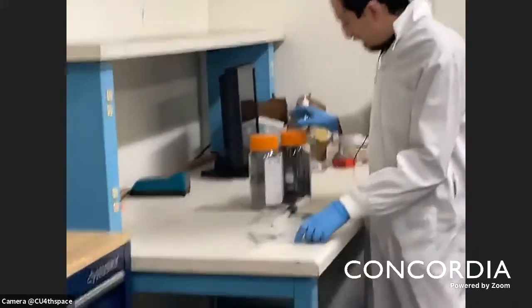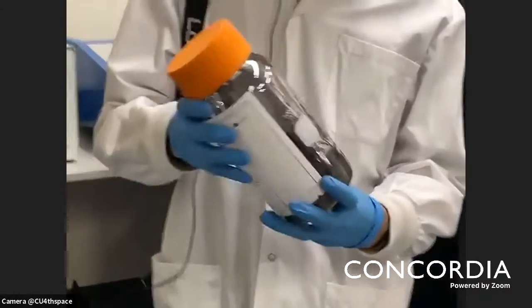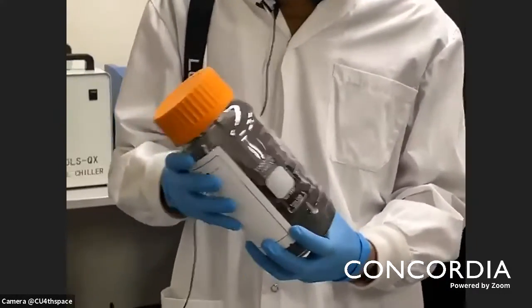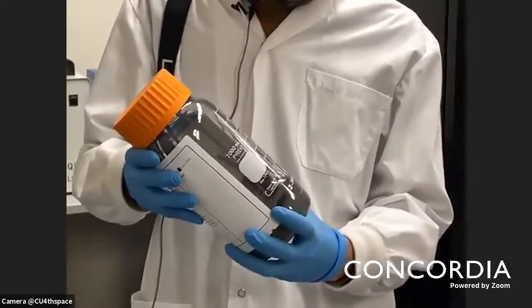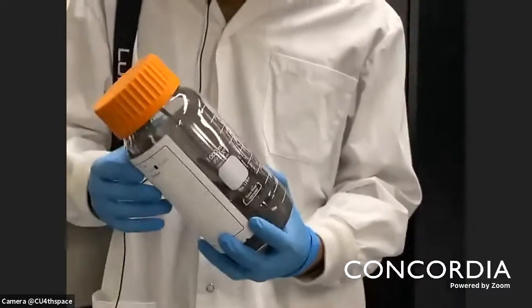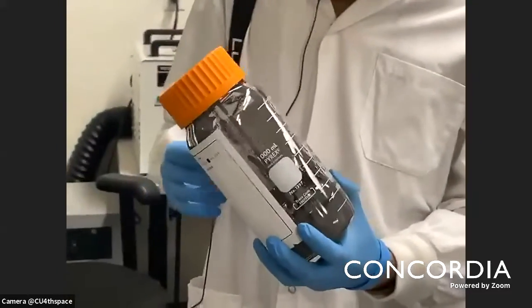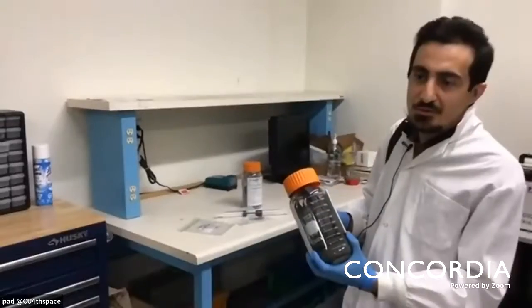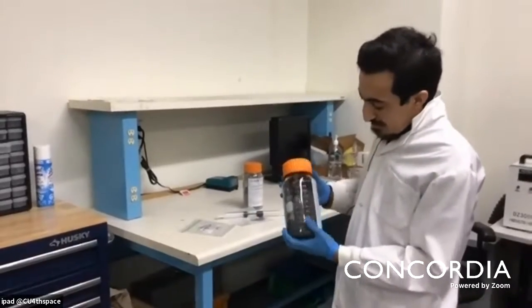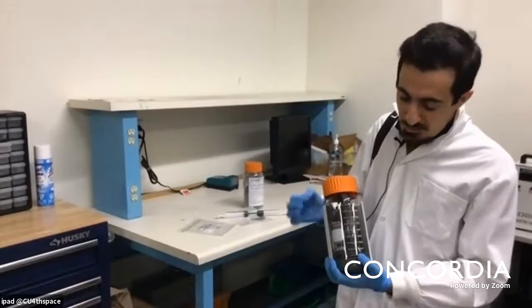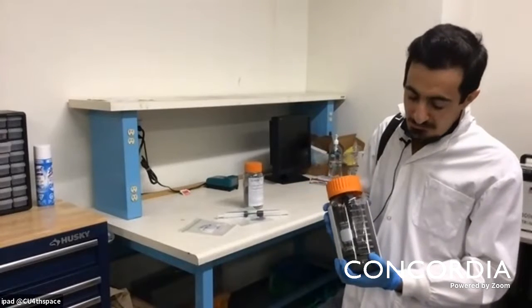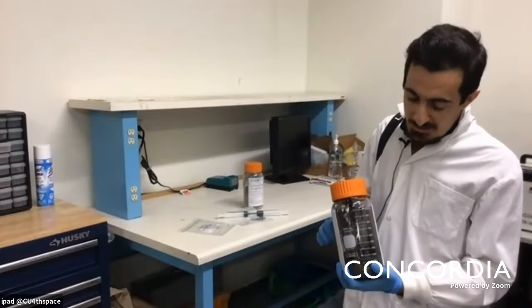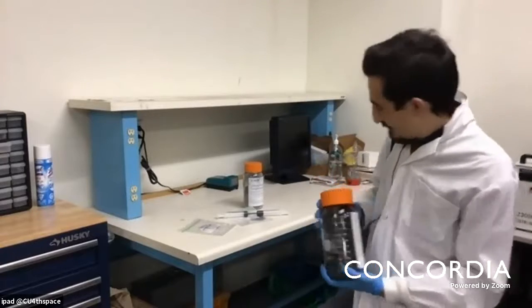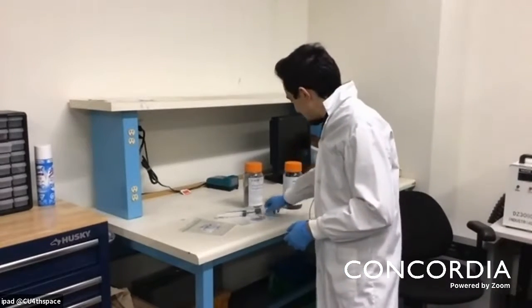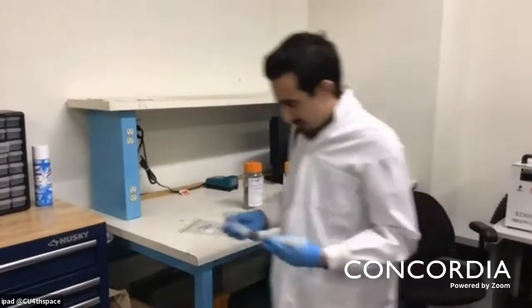Here we have a kind of MRF. This MRF consists of iron particles and a kind of oil. Here it's a silicone oil. These iron particles are inside the silicone oil, and upon applying the magnetic field, the iron particles create a kind of chain-like structure in the direction of the magnetic field. This is a kind of application of this MRF.